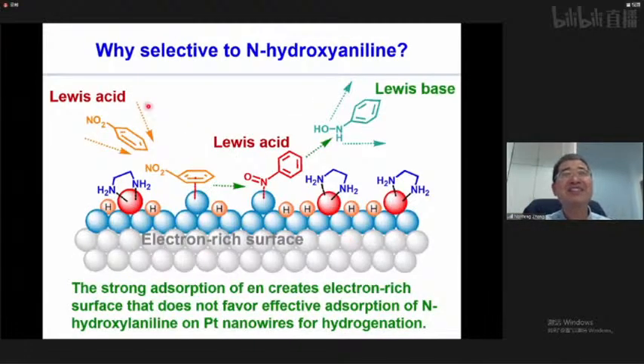So actually, with this in mind, I think the mechanism is quite simple. We have a binding of ethylenediamine. Then we can induce the formation of an electron-rich surface. So all those exposed sites are more electron-rich. For this, the nitroaromatic is electron deficient, so they like to bind on this electron-rich surface. Once we form hydroxyaniline, it's electron-rich. Sorry, they are not welcomed by this electron-rich surface. So they are taken out from the surface.